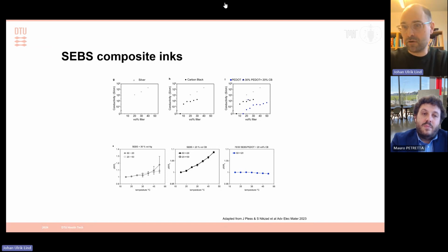In terms of how much you can load, I would say we typically can go up to like 60 or 70% of volume in the final ink. So that's quite high, I would say. So only 30% binder, but you compromise stretchability typically, which is something we're interested in.